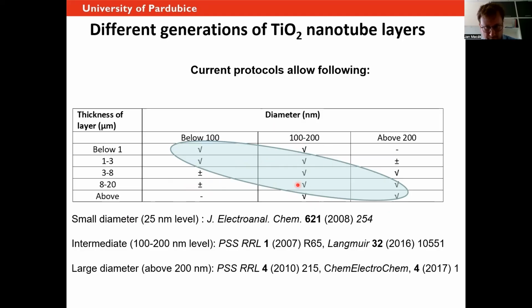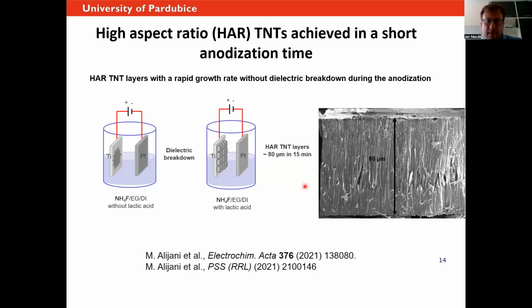So this is the executive summary of the dimensions that are feasible these days, especially in the range of 100 to 200 nanometers. There are lots of options for making tubes from 1 to several hundreds of micrometers. And I'm actually very proud that recently we have achieved, I would say, a significant milestone in the synthesis of the tubes in short time. Because if you want to grow really thick tubes, which are typically the most useful for many applications, you normally need many hours, like 12 hours, 24 hours. And especially with the costs of energy these days, it would make sense to make this process much shorter. And we were able to actually do it by adding lactic acid into the electrolyte.